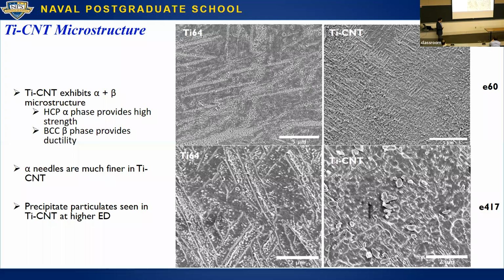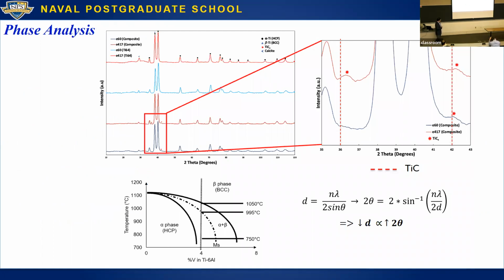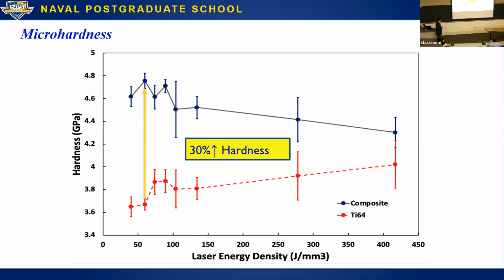So we have a pretty good intuition that these are actually carbides. And in fact, X-ray diffraction did show that we were forming some sub-stoichiometric titanium carbide, which is commonly the type of carbide that you get in selective laser melting because your kinetics are so fast that not all of the carbon interstitials are able to be filled, and you get this sub-stoichiometric phase. So we knew we had titanium carbide, which was certainly not the goal, but you'll see later that we did retain some of our CNTs. This was our main result that we got in terms of mechanical testing so far that I have here.